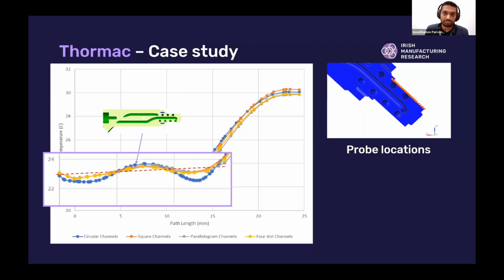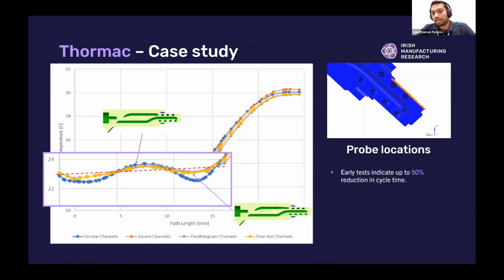So the other approach we used is to replace the circular channels with square profiles. And with the square profiles, again, we noticed there are issues between the channels. So that's where we use the parallelogram profile, because the slanted edges of the parallelogram are exposed to the surface, so they aid in cooling the surface a little bit more. And all of this is done with the knowledge we gain from running numerical simulations in Siemens SimCenter 3D. We then printed the parts, and early tests indicate up to 50% reduction in cycle time.